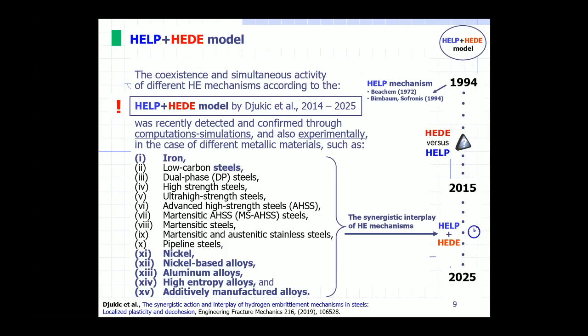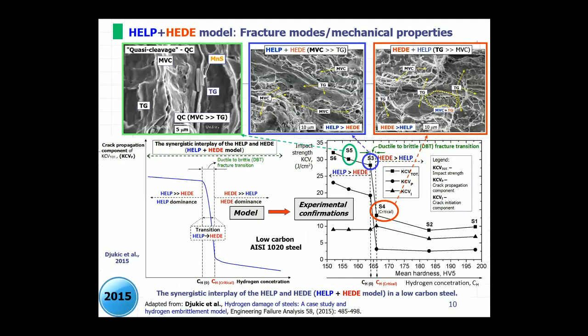I can say that the HELP plus HEDE model is nowadays confirmed in almost all metallic materials, as you can see in iron, also in all types of steels, including low carbon steel, high strength steel, martensitic steel, and very recently, the HELP plus HEDE model and transition of the mechanism is confirmed in nickel, also in nickel-based alloys, in aluminum alloys, in high entropy alloys, and more recently, also in additive manufacturing alloys. Here is the first paper from 2015, in which we proposed the HELP plus HEDE model. As you can see, here we have hydrogen concentration on the x-axis and, let's say, ductility or crack propagation resistance on the y-axis.